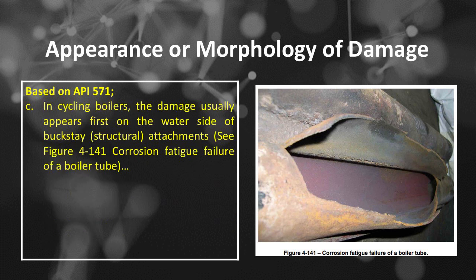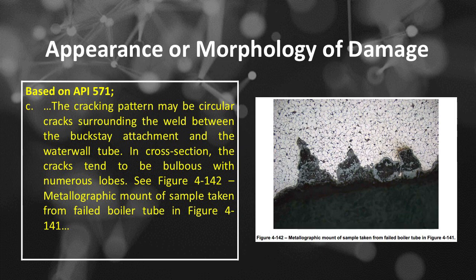Number C, in cycling boilers, the damage usually appears first on the water side of buckstay structural attachments. See Figure 4-141, corrosion fatigue failure of a boiler tube. The cracking pattern may be circular cracks surrounding the weld between the buckstay attachment and the waterwall tube. In cross-section, the cracks tend to be bulbous with numerous lobes. See Figure 4-142, metallographic mount of sample taken from failed boiler tube in Figure 4-141.